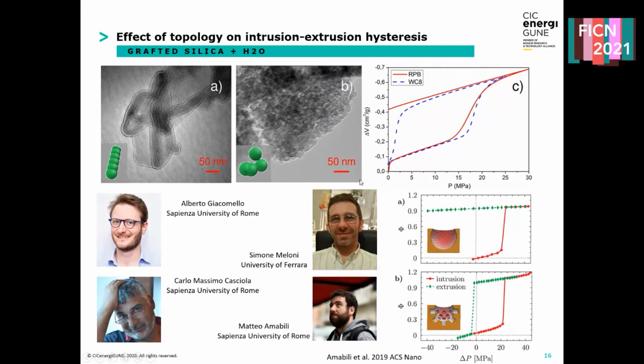So here we looked into how the topology of mesoporous silica affects the intrusion-extrusion hysteresis. It seems that both experiments and MD simulations suggest that providing conditions for the bubble nucleation during the extrusion is highly important to reduce the hysteresis in the cycle, and in fact in this case is to permit the reversibility of the intrusion-extrusion process.